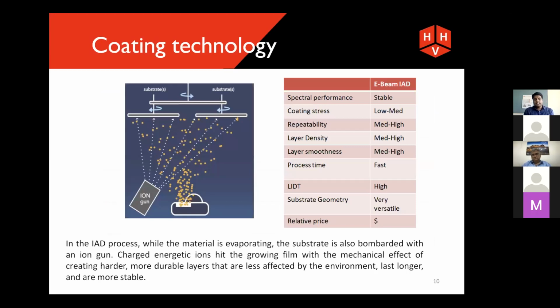The coating technology that we use is ion-assisted electron beam deposition. There are various types of coating techniques available. Ion-assisted electron beam deposition is a low-cost, high-speed process, and it has higher versatility. In the IAD process, while the material is getting evaporated, the substrate is bombarded with an ion gun. The charged ions hit the growing film with a mechanical effect, creating harder, more durable films that are less affected by environmental changes. They last longer and they are more stable.